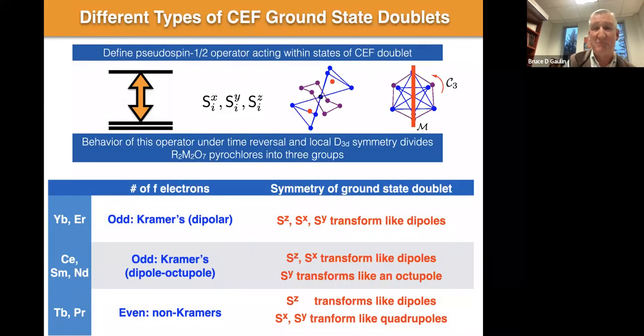Knowing that, we can look at some of the symmetry properties of this pseudospin 1/2 degree of freedom. Just by virtue of the fact that you've got a crystal field doublet, which is well separated by about 50 or 60 meV from the next excited state doublet, which is in turn separated by another 50 or 60 meV from the highest energy doublet. Just by virtue of the fact that these two states are separated by some large energy gap to all the other crystal field states, the fact that you've got a degeneracy of 2 here tells you that you've got a pseudospin 1/2 operator that is relevant for whatever the degrees of freedom are that are associated with the cerium 3+. And now, because we know what these wave functions are, we can write down the X, Y, and Z components of the pseudospin 1/2 degree of freedom.